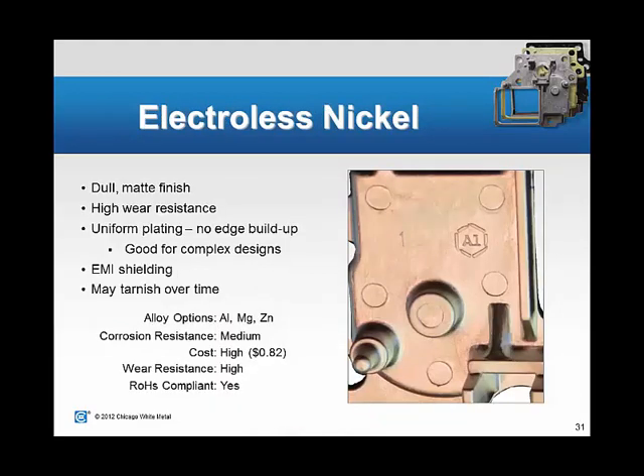The next option we look at is Electroless Nickel. It provides a dull matte finish with a very high wear resistance, has a very uniform plating, and is good for very complex features and complex design parts. Again, it has excellent EMI shielding capabilities. It may tarnish or darken over time, which is something to just be aware of, but it is a very nice finish. It is used on all three alloy types, medium corrosion resistance, higher end of the cost range of the processes that we look at, 82 cents, a high level of wear resistance, and again, it is RoHS compliant.